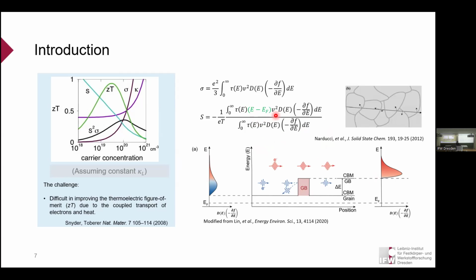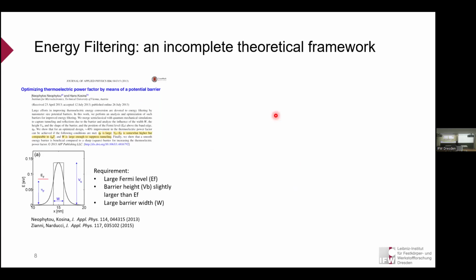People have been talking about it in the community for quite some time. If we want more detailed guidelines on how to realize a performance gain, we have to play with the math, and several groups have already done this kind of work. The conclusion drawn from these works is that there are several requirements. We need a high Fermi level, meaning heavily doped or even metallic materials. The barrier height has to be higher, but not too much, only slightly higher than the Fermi level. We also need a wide barrier width to effectively reduce the tunneling effect. Combined together, you have the opportunity to enhance the thermoelectric performance.